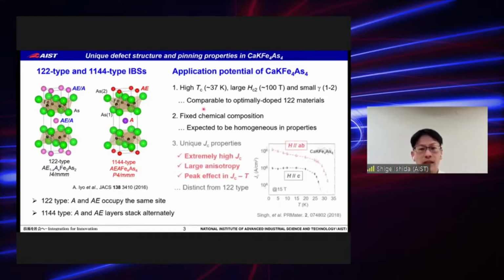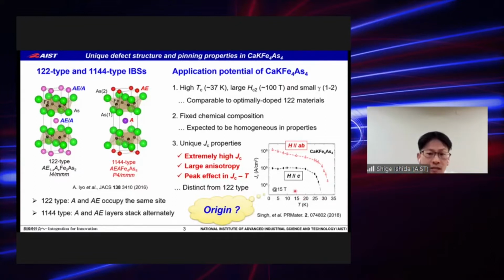Moreover, it has been reported that calcium potassium 1144 shows extremely high Jc values with a large anisotropy against magnetic field. Also, when you see the temperature dependence of Jc, once Jc goes down with increased temperature, but it slightly increases with further increased temperature - a kind of peak effect in temperature dependence. These Jc properties are distinct from the 122 type. Revealing the origin of these unique Jc properties is very important for applications as well as vortex physics.